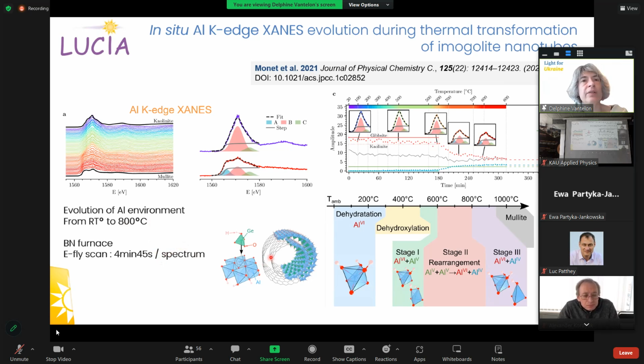And so the users followed the transformation of the nanotube of the imogolite to layers with a mullite-like structure. And during the heating in situ, they could observe the transformation of aluminium with the XANES from octahedral organization to pentahedral and then tetrahedral. I have to mention that this was measured with macro beam. So macro beam has also an interest, not only micro or nano.